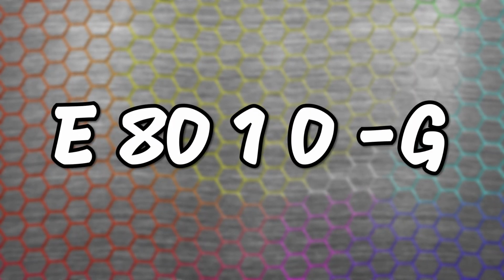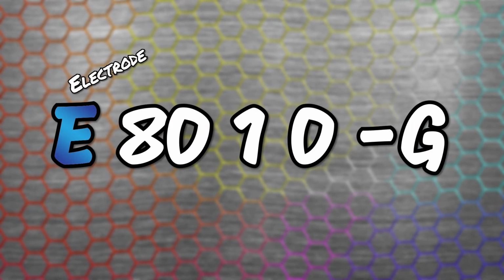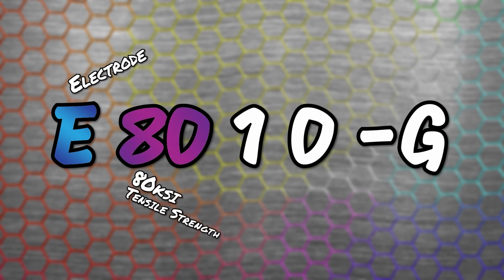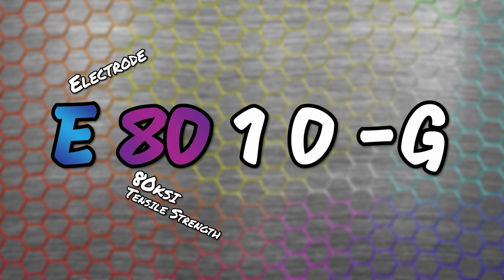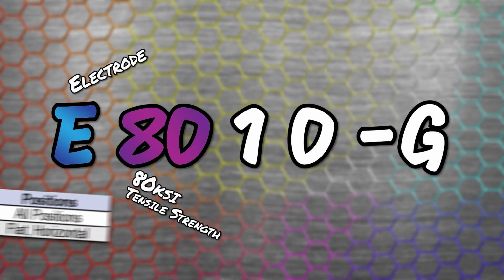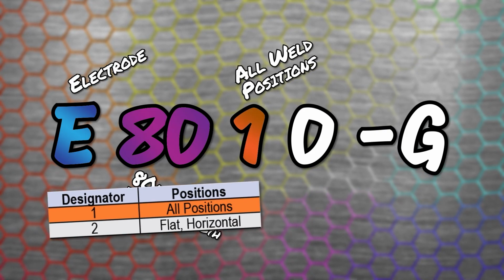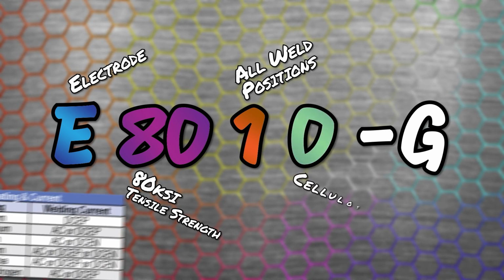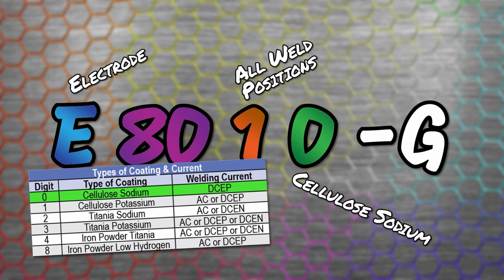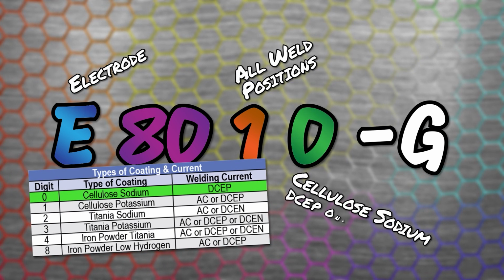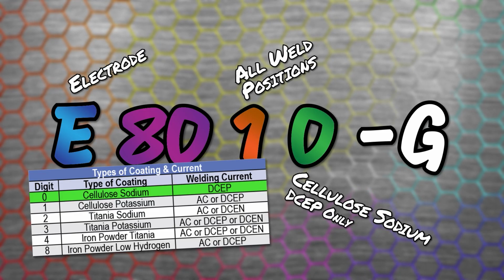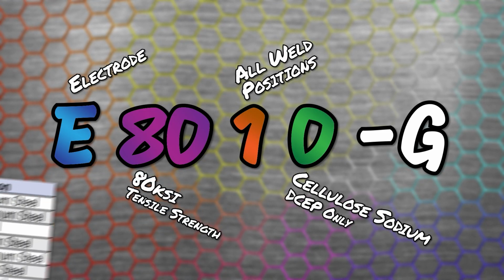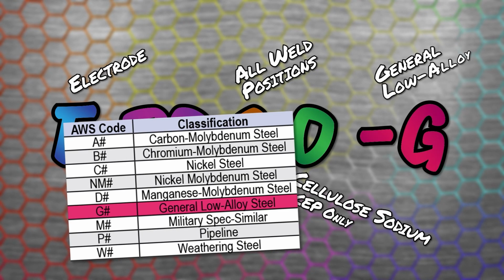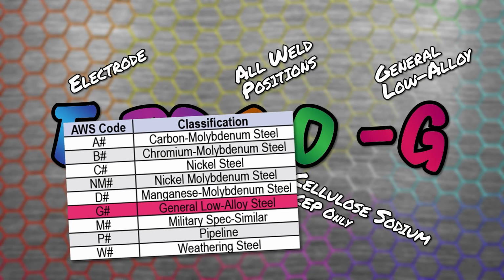E8010-G. It's an electrode, has 80 KSI tensile strength, welds in all positions, has a cellulose sodium coating that can only weld with DC electrode positive power. And the weld metal will be a general low alloy composition.